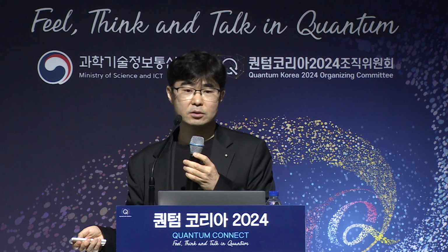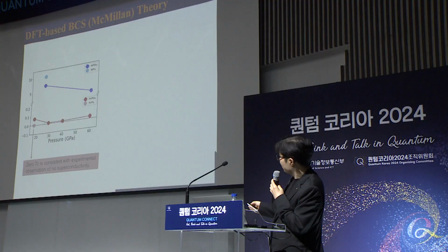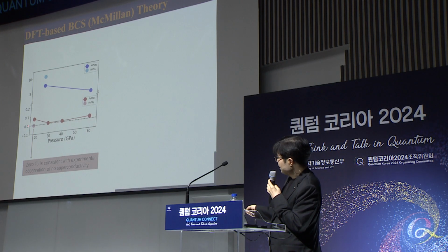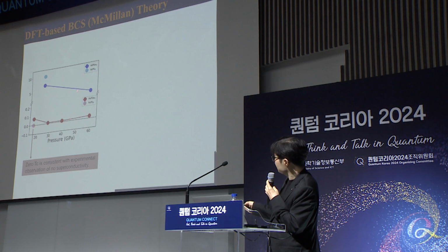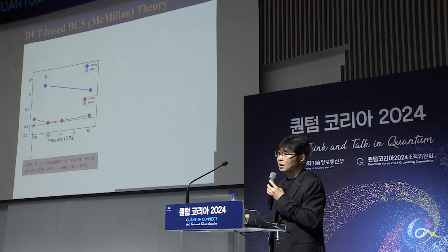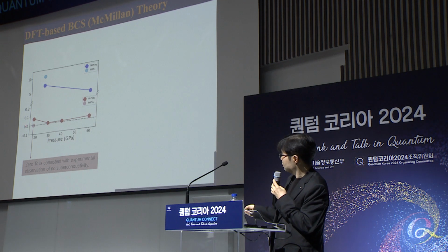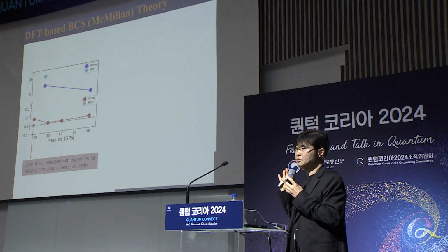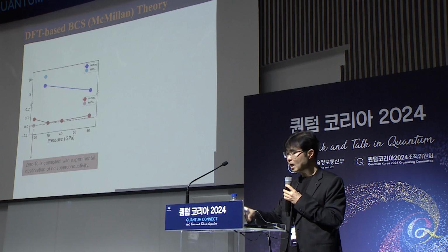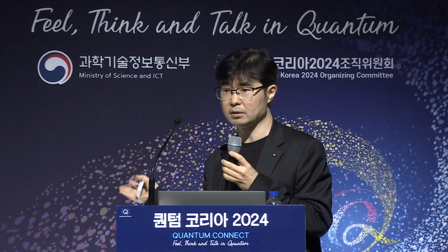For me, these two materials are very, very promising to become superconductors, even if I cannot tell you the details here. Based on this information, we finally estimate the superconducting TC. This y-axis is the superconducting TC, and there are four different materials. Let me first look at this point, which is about FePS3. My calculation tells me that this superconducting TC is 0, which means it is very unlikely to become a superconductor, and it is consistent with experimental observation, because experimentalists could not find superconductivity for this material.